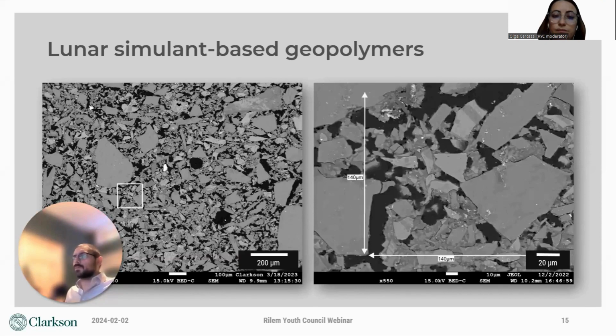Not all the geopolymers work well. Here's another sample with a different simulant and a different alkaline activator. Even in the very zoomed out view of the microstructure on the left, you can see that it's much coarser and more discontinuous than the previous one. In the close-up view on the right, you can see how the simulant particles are no longer well connected. The paste matrix between them is sparse and poorly refined, and this suggests to us that this combination of activator and simulant would perform poorly as a geopolymer.